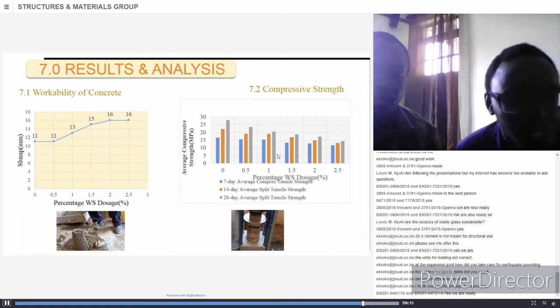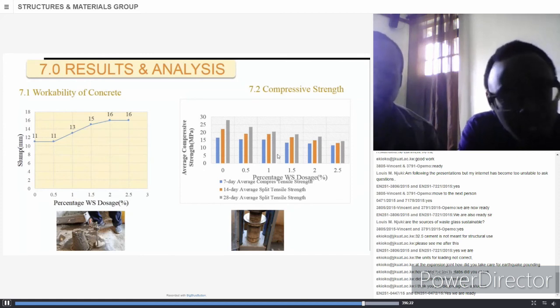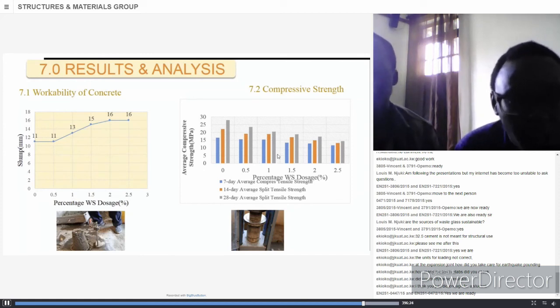Now to the results and analysis. We can see from this graph on workability that the workability was observed to increase compared to that of the control. The control had a workability of 11 millimeters, and as we continued dosing the quantity up to 2.5%, we see that the workability increased.